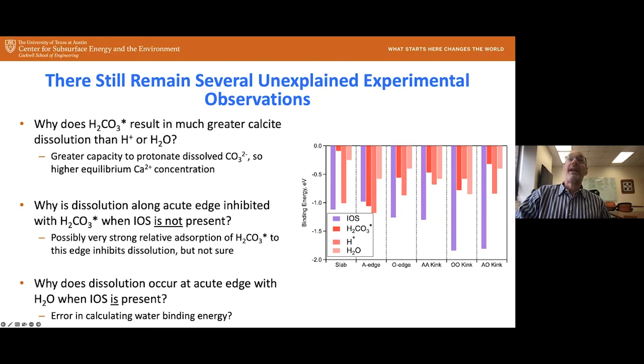I wish we could explain everything with our results, but there are several unexplained observations. One, I think, can be addressed fairly straightforwardly. Why does the carbonic acid result in much greater calcite dissolution, meaning a much higher calcium concentration in solution, than the proton or the water? Well, carbonic acid has buffering capacity, two protons per carbonic acid. We also have a partial pressure of supercritical CO2 in a separate phase above the liquid. So we have a lot more capacity to protonate the carbonate as it comes off the calcite, and our equilibrium concentration of calcium is much greater. That can explain why we have much greater dissolution with the carbonic acid.